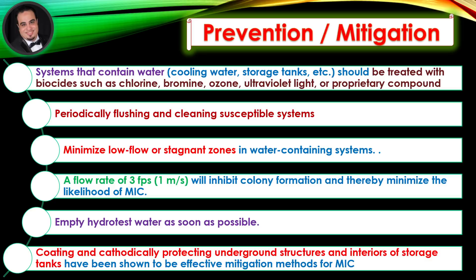Empty hydro test water as soon as possible. Coating and cathodically protecting underground structures and interiors of storage tanks have been shown to be effective mitigation methods for microbiologically influenced corrosion.